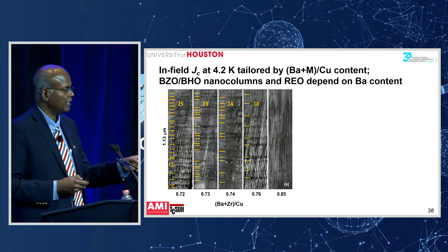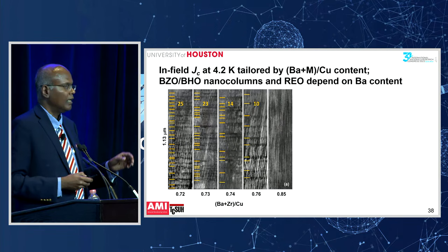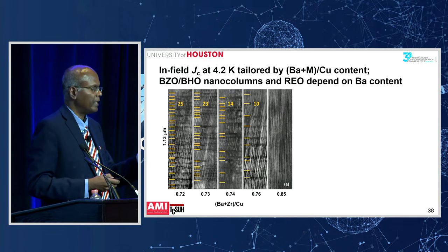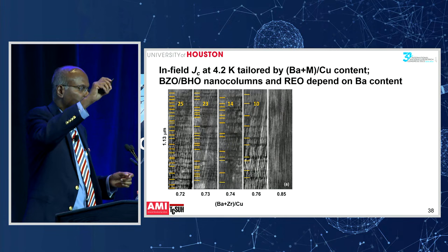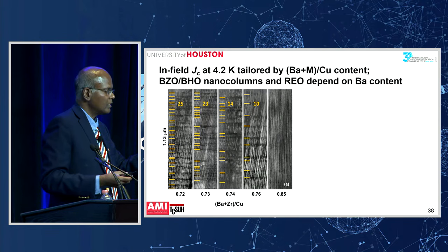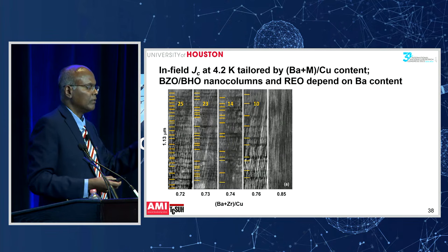You can actually see the effect also in these cross-section TEM images. So what I'm showing here, from left to right, is the barium plus zirconium over copper, which is essentially increasing the barium content from left to right. So what you can see is the aligned barium zirconate nanocolumns, right? You can see all the vertically aligned barium zirconate nanocolumns, that's what you want. But you also see some precipitates horizontally, along the ab plane. These are rare earth oxide precipitates. They're also good, but they're not as effective as barium zirconate nanocolumns.